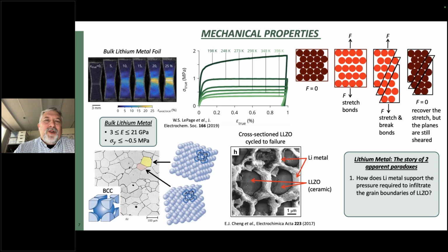And so an intuitive solution would be, well, let's just get rid of the grain boundaries, right? They clearly must be the weak spot. We'll just make a separator out of a single crystal. Well, they've gone down that road, and lo and behold, the outcome is exactly the same. The lithium just finds another defect to exploit instead of the grain boundaries, okay?